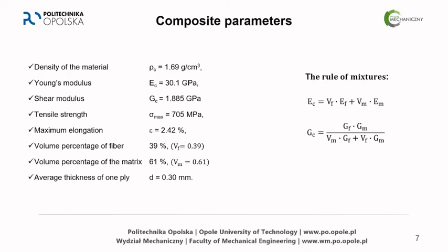From here, I would like you to see the second and the third lines, which is Young's modulus and shear modulus, which we're calculating based on the rule of mixtures, which is presented on the right of this page. As you can see, the value of the modulus in the composite depends on both modulus of both fibers and matrix. F is for fibers, M is for matrix, and also based on how much reinforcement we have. So based on it, we could assume a value of the Young and shear modulus in this composite.